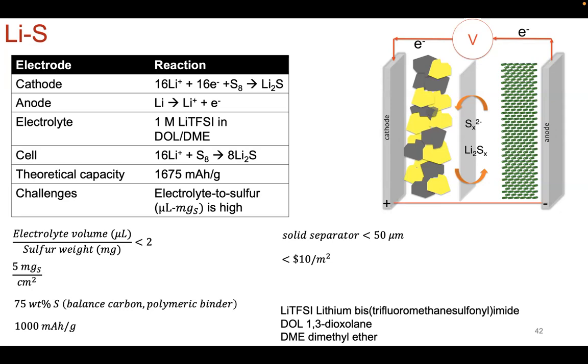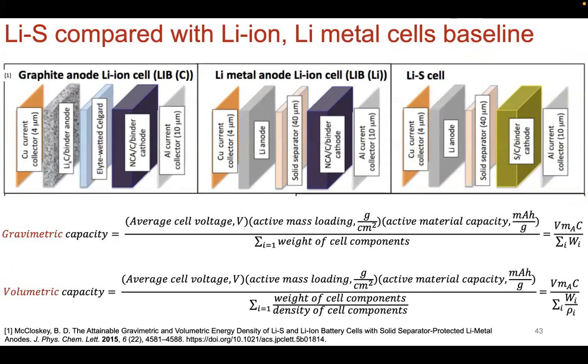So the research thrust behind prevention of polysulfide shuttling for the last 20 years has been on that. Many things have been tried. Not everything has been that successful. And it really comes down to comparing apples to apples. Just because an additive works at a certain sulfur loading or a certain electrolyte loading doesn't mean it translates when you try to increase the sulfur mass loading. It's a totally different ballgame when it comes to solubility of sulfur and lithium polysulfides and the polysulfide in the electrolyte and in the catholyte. So it's all very nuanced, and the parameters change. So I'll go into exactly the ranges in which lithium sulfur could be competitive.